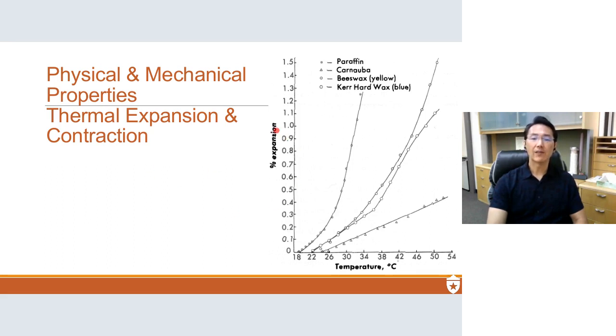So in this graph, what we have is percent expansion and the temperature. And you can see that as you heat it up, you don't get a straight line. You get curves, and it's not consistent all the way through. And you do have straight portions, right? There are times when certain waxes will have multiple breakpoints where there's one coefficient of thermal expansion, and then once you pass a certain temperature, you have another one, and then at a certain temperature, you have another one. And those correspond to different glass transitions for different parts of the wax, and that's why we have that. So the shrinkage and expansion is not as easy as most materials. Okay, carnauba has a very low coefficient of expansion, and it's because of the strong secondary valence forces due to the high concentration of ester bonds on here. So that allows it to act more normal, I guess. Okay?